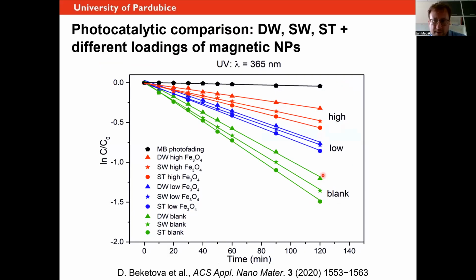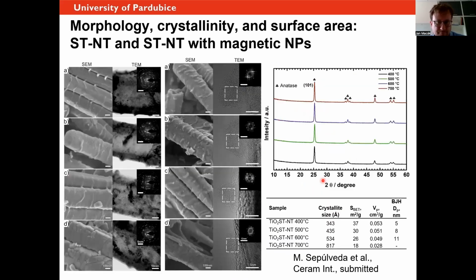So the key thing that I would like to highlight here is that the single tubes, really, when they're separated, have the best performance compared to the single wall and double wall tube. So there is something in it when I say that we have even more surface area with the single tube powders. When you decorate with the nanoparticles of magnetite, they are obviously shaded, so the performance goes a bit lower. But the message that I'd like to say here is that by this time, it is possible to make tubes as such, tubes which are super pure, so a little bit etched, and also nanotube powders.